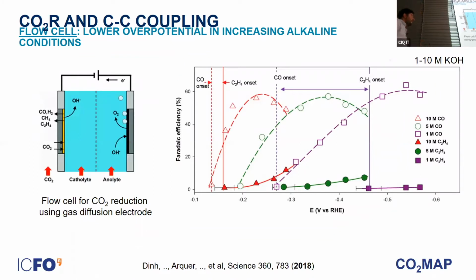So in one of our early works in 2018, we first changed the reactor type, moving away from these aqueous type of reactors into a reactor called a flow cell type of reactor, where the reagents are provided from the gas phase. So instead of dissolving CO2 in water, which has a limited solubility, you just flow CO2 through a gas diffusion layer. You can be much more efficient. And one reason that allows you to be more efficient is that by using these flow cell reactors, you can change the electrolytes a lot. And now you can use very alkaline media. And this changes a lot how this reaction proceeds.